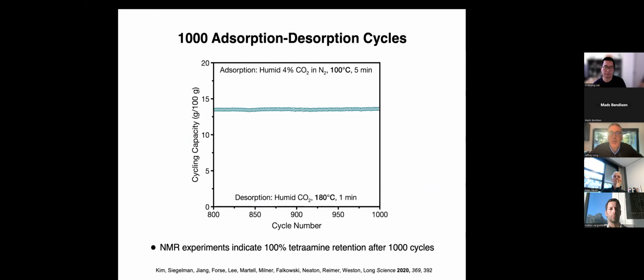In fact, you can capture from an NGCC flue gas stream at 100 degrees C and have essentially negligible water coadsorption. And then desorb under various conditions, including going to say 180 degrees. This is showing the last 200 of 1,000 desorption cycles, showing that we're not losing any capacity for CO2.